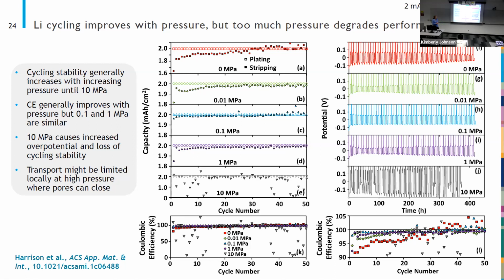So on transport, we hypothesize that the reason the high pressure doesn't work very well is because we can shut down pores in our porous polymer separator, such that transport is limited and we are essentially not able to move ions quickly enough in this cell anymore. So I'll talk more about that in a few slides. But first, what I want to show you is the morphology evolution with pressure.